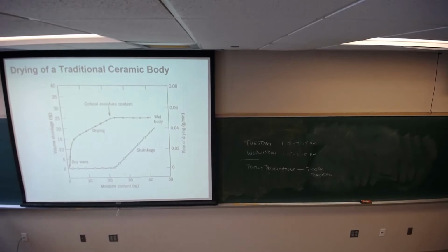Constant rate period, okay? When it's corrected for shrinkage because you're losing surface area of the piece with shrinkage, right? When you get to the point where the water has receded into the pore structure, you no longer have any more shrinkage, okay? So your opportunity for damage occurs in the system basically at this point. At the end of shrinkage is the last chance you have for damage in the system. Now that's generally true when you have water left in the pores, but there's no more shrinkage, there's no more rearrangement. In the absence of rearrangement, right, there's no strain in the system ideally. That doesn't mean you can't blow the part up potentially if you were to heat it excessively high, right, so that you can generate steam, but we don't consider that to be reasonable.